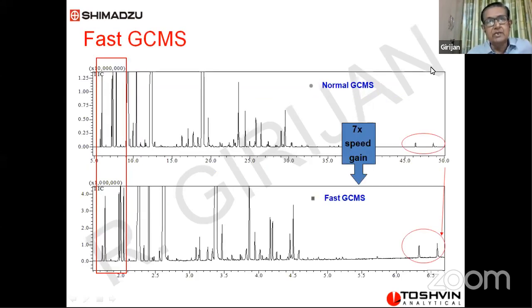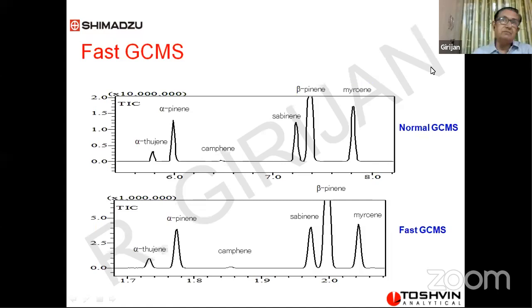For example, there's a perfumery compound. There are two spectra, TICs, shown, one at the top and one at the bottom. The top one is a normal GCMS. It's a perfumery compound, so many compounds are coming from the sample. And it has taken more than 50 minutes, approximately 1 hour, for the run to complete. The same sample is analyzed under fast mode of analysis, and the analysis is getting completed in less than 10 minutes' time. That means in 1 hour, I'll be able to analyze at least 5 samples. That means I'm increasing my output fivefold.